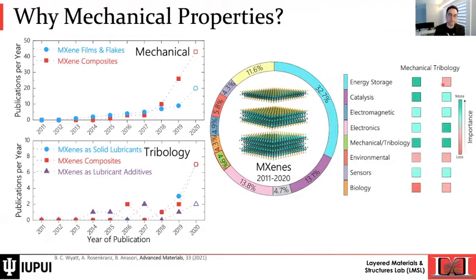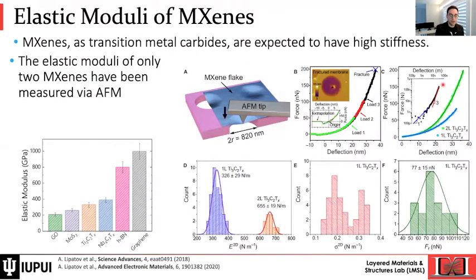Now, how much do we know about the mechanical properties of MXenes? We only know, measured, the 2D stiffness and also the elastic moduli of two MXenes only: niobium 4 carbon 3 and titanium 3 carbon 2. For these two MXenes, the elastic modulus from their 2D modulus was measured. Both were done at the University of Nebraska in collaboration with Drexel University. By AFM indentation, atomic force microscopy, the 2D modulus was measured, and based on the thickness of MXene, the elastic modulus was calculated. You can see that we are in the 300 to 400 gigapascal range.